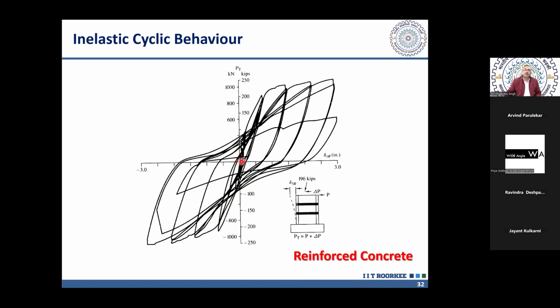So you can see that initially the slope is quite high. So this is the slope of the initial load displacement curve. And in successive cycles, it goes on reducing. You can see that the slope is reducing. So the stiffness degrades in cyclic loading. So under cyclic loading, stiffness of RCC structure does not remain same as we have obtained using moment curvature relationship, or by multiplying EI with the so-called stiffness modifier. So that stiffness does not remain same.